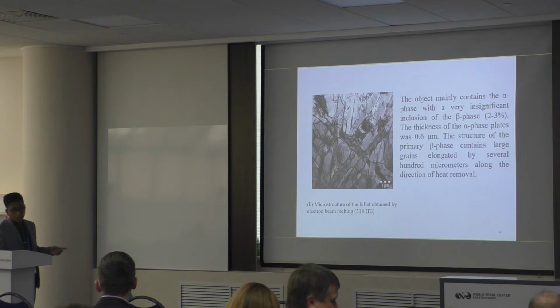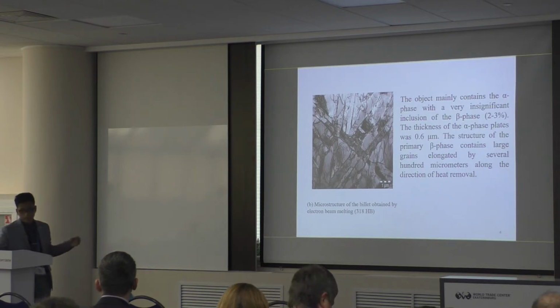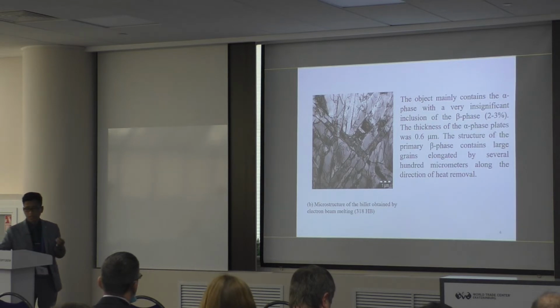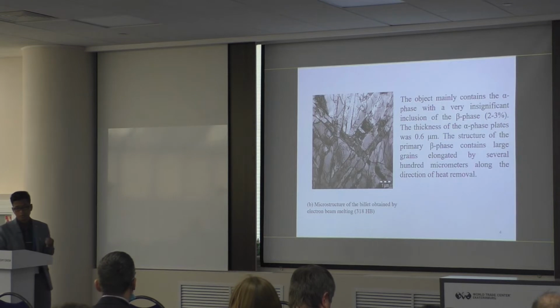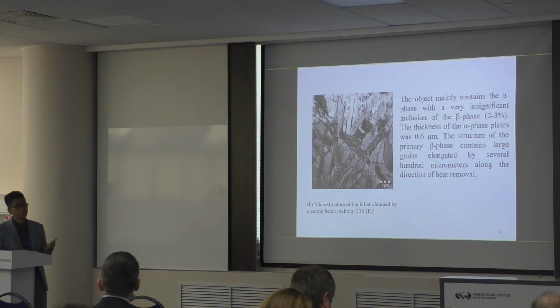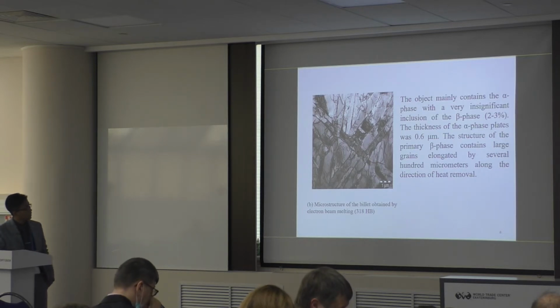Figure B, the workpiece obtained on the Arcam A2 selective electron beam method unit, was obtained as follows. A layer of powder with a thickness of 50 micron was successively applied to a stainless steel platform preheated to 750 degrees Celsius. And the speed of the electron beam was 1200 millimeter per second. The hardness of the material is 380 HB.